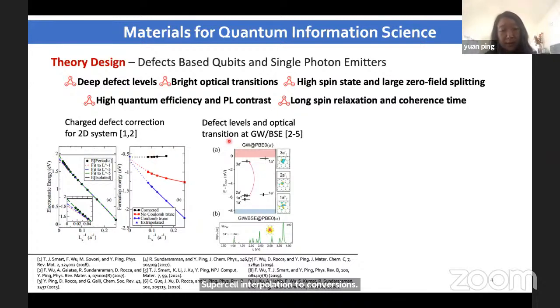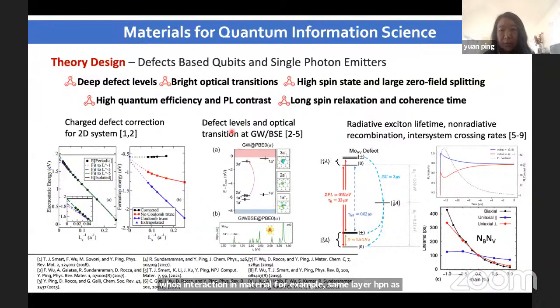And then we apply the GW-BSE calculation to compute the defect levels and the optical transition, including electron-hole interaction. This is also necessary because they have very large electron-hole interaction in materials, for example, thin-layer hBN. At the end, with the electronic structure and optical property, we look at the radiative and non-radiative recombination. As this example shows, we designed a divacancy with Mo defect in hBN. And more importantly, we also computed intersystem crossing between triplet and singlet, and it's a necessary step if you want to initialize the qubit.